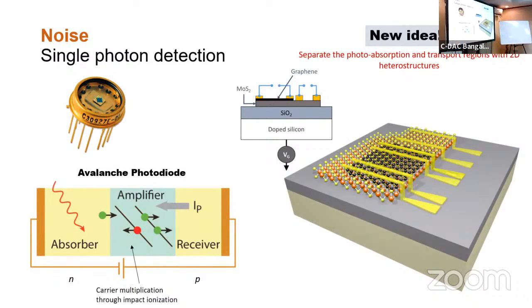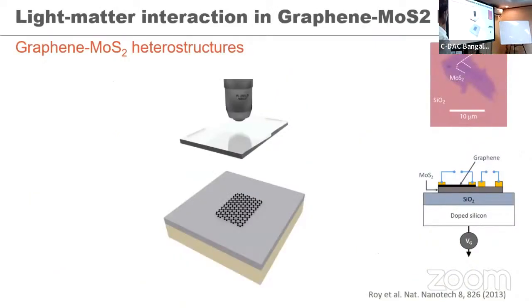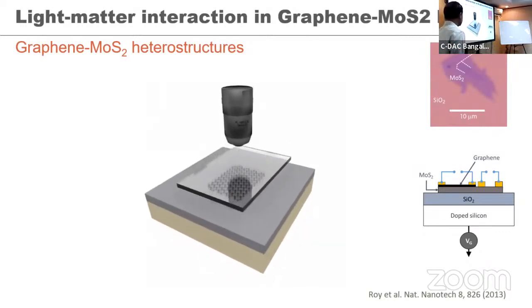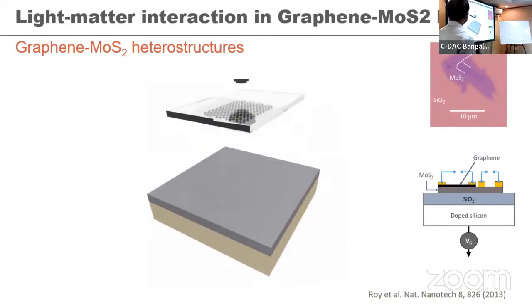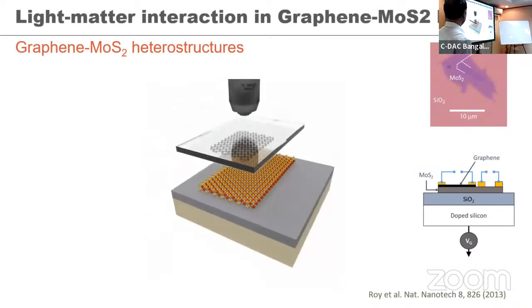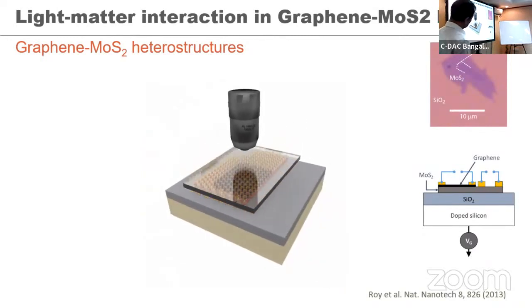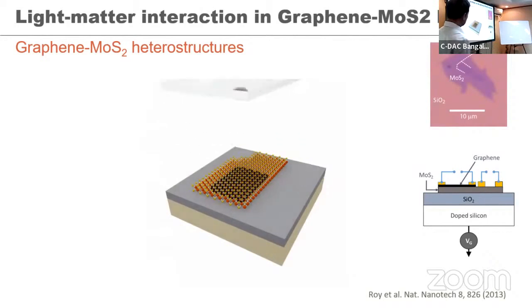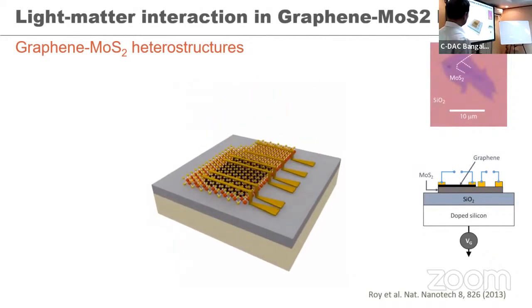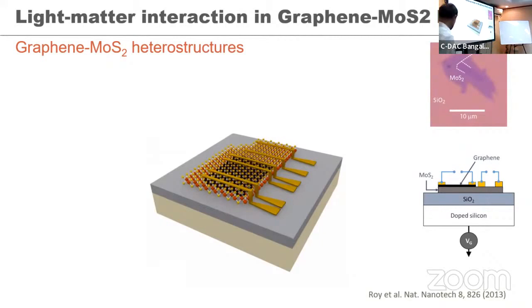That was the neat idea that we started doing, and as I said, it is nothing but using the same kind of generation. So essentially you take a graphene layer up, then you put that on a molybdenum disulfide, and then you put electrical contacts to measure the current. That's the basic idea.